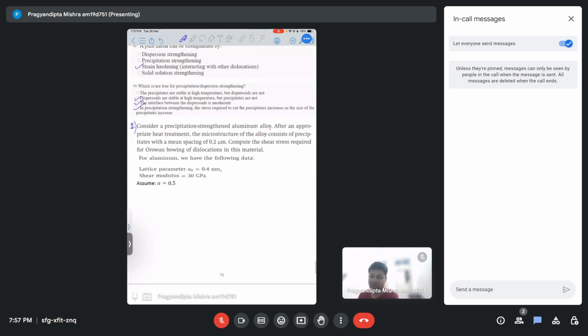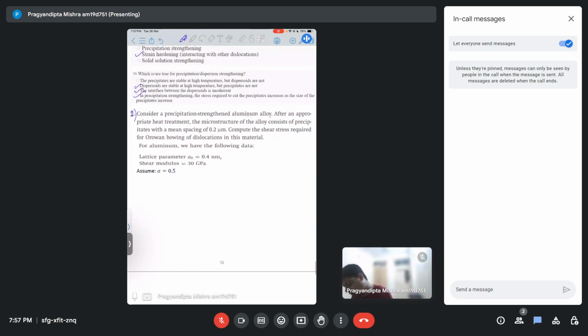Okay. This is question number 11. Consider a precipitate strengthened aluminum alloy. After an appropriate heat treatment, the microstructure of the alloy consists of precipitates with mean spacing of 0.2 micrometer. Compute the shear stress required for Orowan bowing of dislocations of this material. They have given you the lattice parameter, the shear modulus, and also the alpha value.